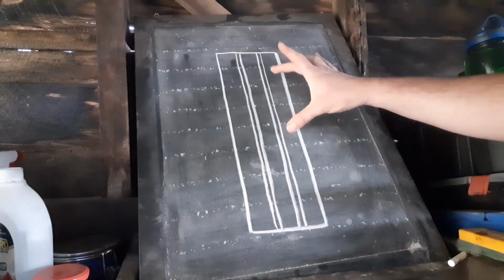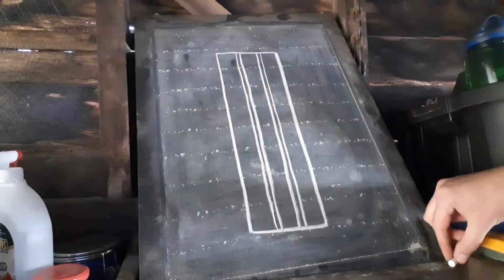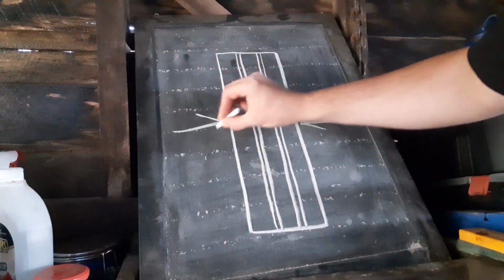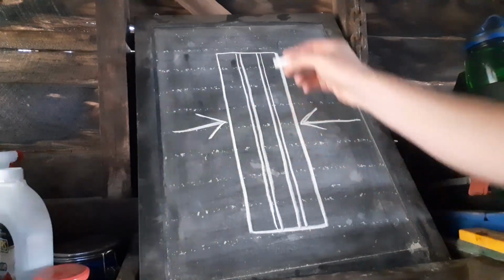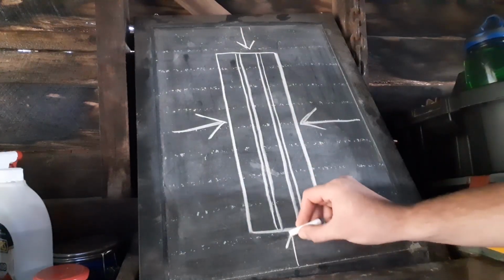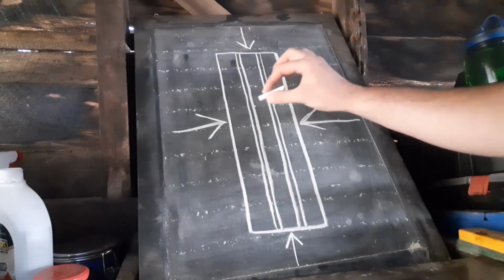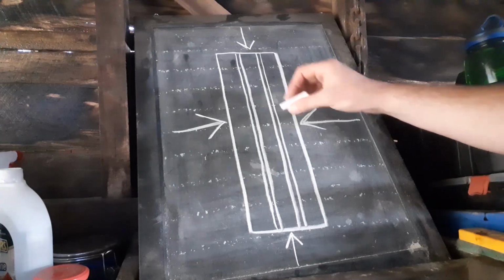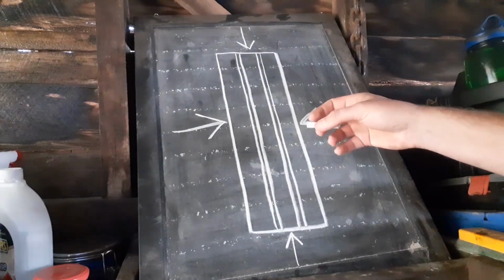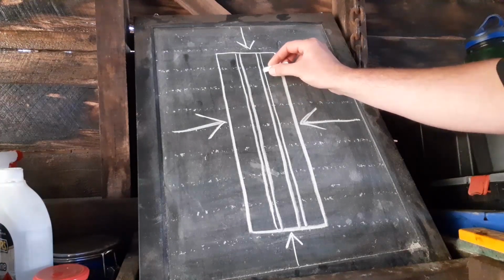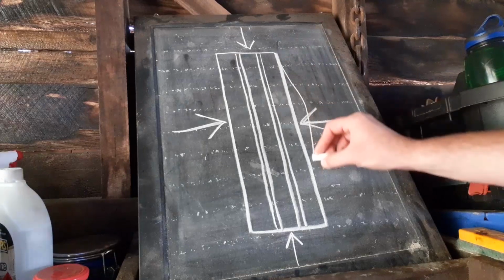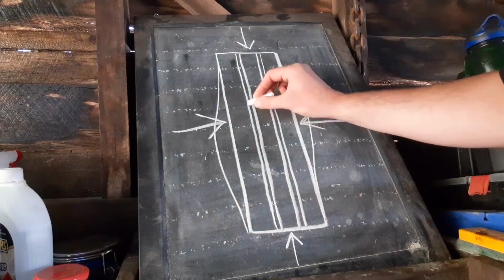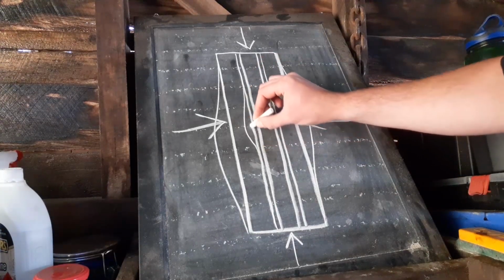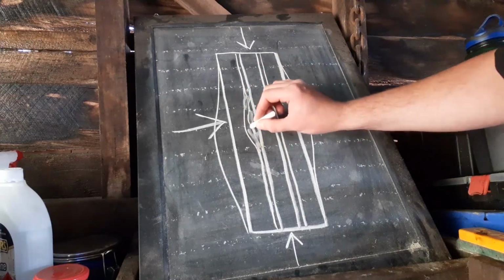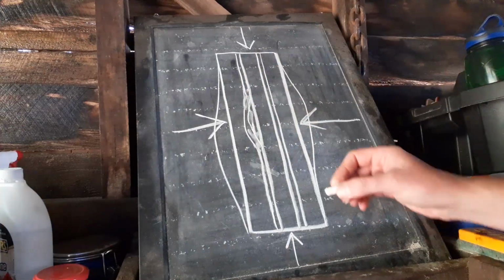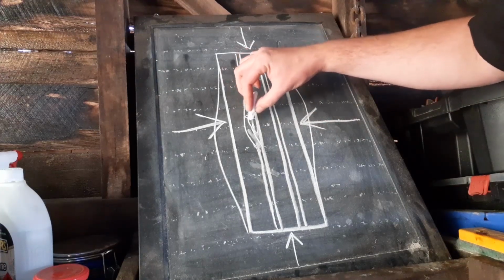Let's say you've got your San Mai billet here. You've got steel, steel, steel, and copper, copper. When you strike this way, or this way, you're forcing the copper and the steel together. When you strike this way, or even use compressive force, like a press, this way or this way, what can happen is that steel and copper bend at different rates. They deform at different rates, just like different grades of steel can, to a lesser extent, but steel and copper very, very differently. And so when you strike this way, it's going to bow out like this. It's a process called upsetting. But it may actually separate your copper layer like this, creating a delamination. You can see my horrific chalk drawing here. This delamination is basically where the copper has popped away from the steel.